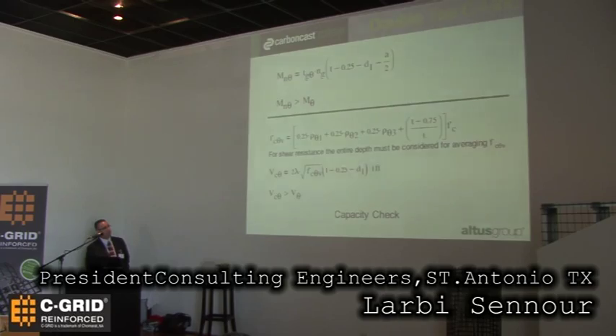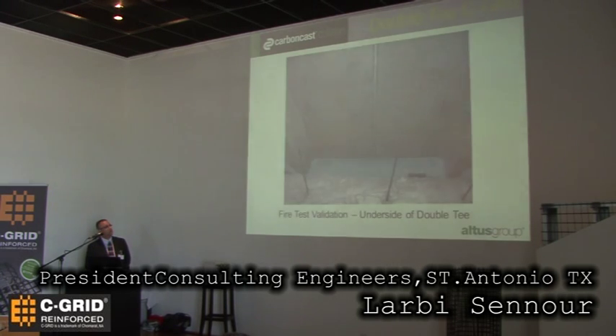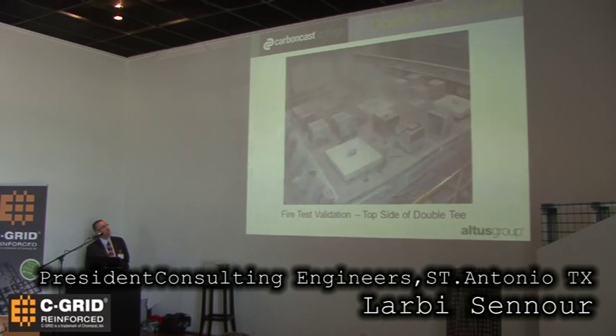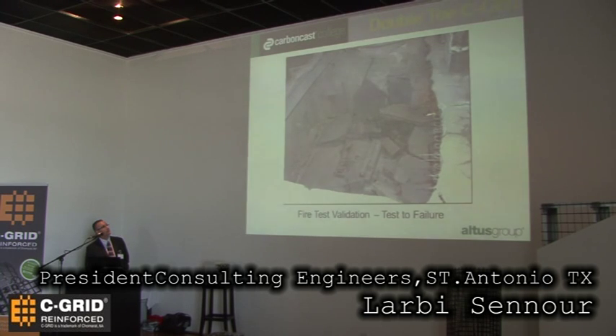So we have a prescriptive method that has been validated by test, and this is the type of test we use. We have a test, double T in a chamber. We load it up under fire until failure. And then you validate. You put all strength gauges, you measure your temperatures, you measure your strength reductions, and everything correlates. So we have that prescriptive method, and it's in our publications as well.